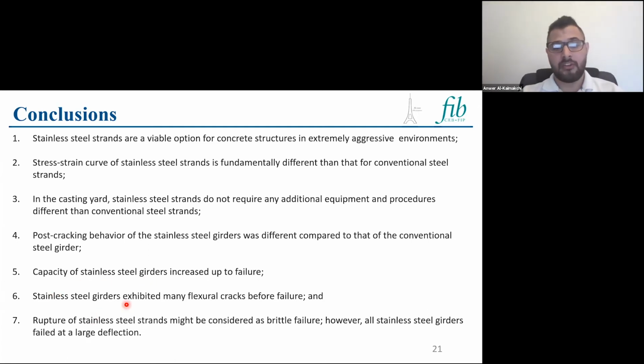The stainless steel girders exhibited many flexural cracks before failure, which is a good indication that the member is reaching its ultimate capacity, which gives us a sign that we need to evacuate or do something. And then rupture of the stainless steel strands might be considered a brittle failure. It is a brittle failure, but in our test, the girders exhibited a large deflection around 5 to 6 inches.